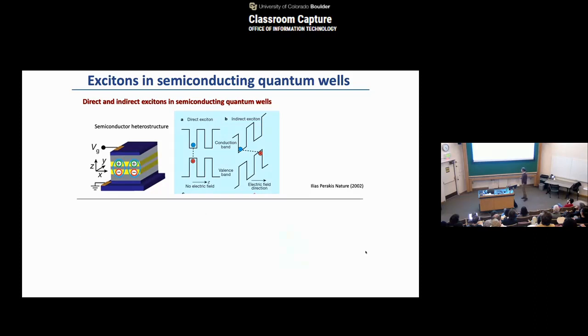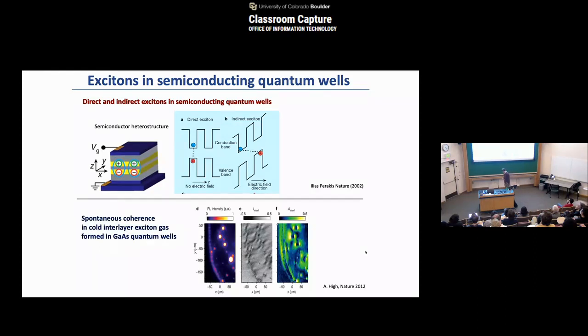Indeed, in the gallium arsenide double quantum well, this work was done, for example, by Alex High at UCSD when he was there. By shining light into the system and creating excitons, the excitons start to generate spontaneous coherence, which is probably the first step to start developing some sort of condensation states. However, it was a really heroic effort, but there are also some concerns there.